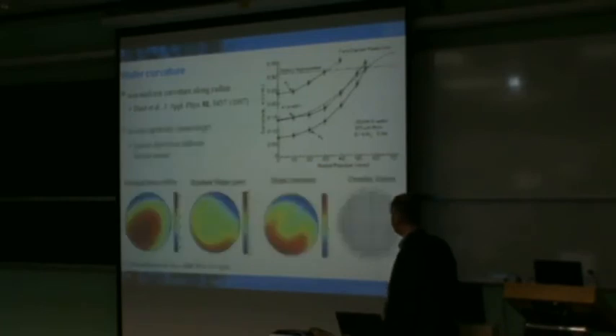And what I'm showing here is work using finite element methods to show how, again, curvature can be changed dramatically when the assumptions of uniform film, uniform stress, and even of bonding between those can change. And so Stoney's approximation here would predict a straight line, whereas we can get some significant changes in that curvature depending on where you are on the wafer and the orientation of that wafer.